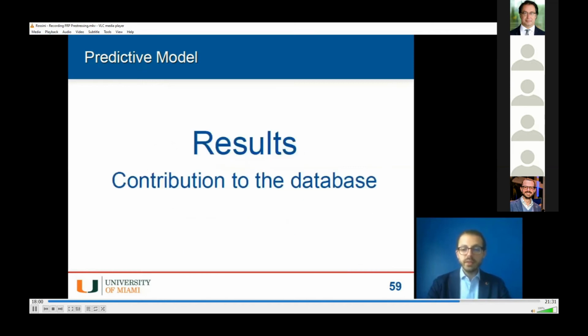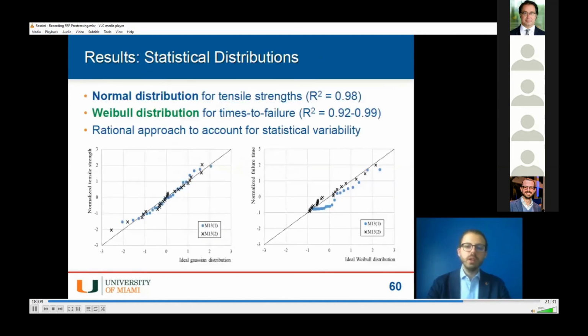Let's see how this translates in actual numbers. Let's see if this model actually worked on the data that we collected. Here you see our statistical modeling. We used a Gaussian distribution for strength and a Weibull distribution for time to failure. You see that in both cases we have quite a good agreement and matching.